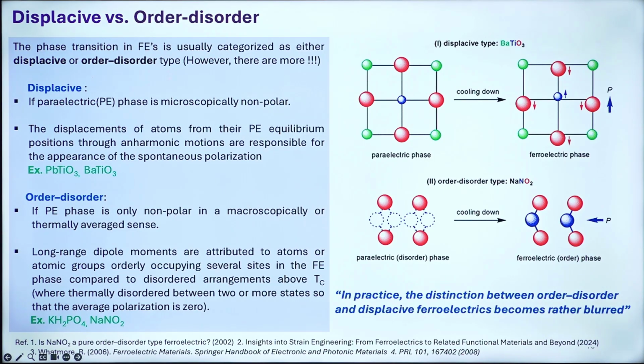So here the paraelectric phase is microscopically non-polar because we don't expect any polarization in that, and then you have a system similar to the barium titanate case. You have a paraelectric system, cool it down, and we see a ferroelectric phase transformation, which is purely displacive. Lead titanate and barium titanate are the classic examples. And then there is another thing which is purely entropy driven, which is order-disorder. If the paraelectric phase is only non-polar in a macroscopically or thermally averaged sense, when you cool down, you get an ordered phase. There the space group changes, going from a disordered to an ordered phase.